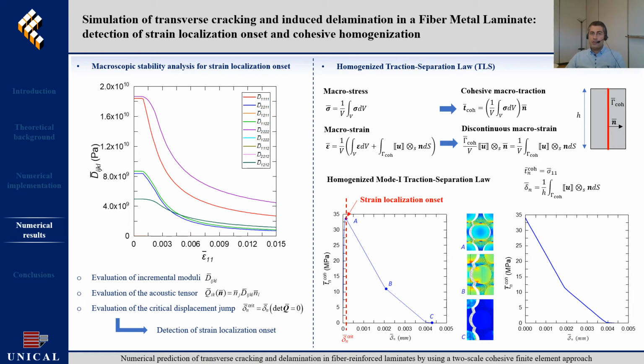This slide presents the additional results obtained from the macroscopic stability analysis performed at different loading steps, starting with the incremental moduli. These moduli are used to compute the acoustic tensor, thus allowing the rigorous derivation of the strain localization onset condition. This condition identifies the critical displacement jump by which the homogenized traction separation law is shifted to the left in order to extract its pure softening behavior.